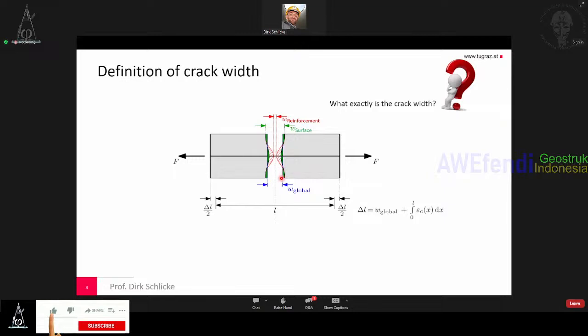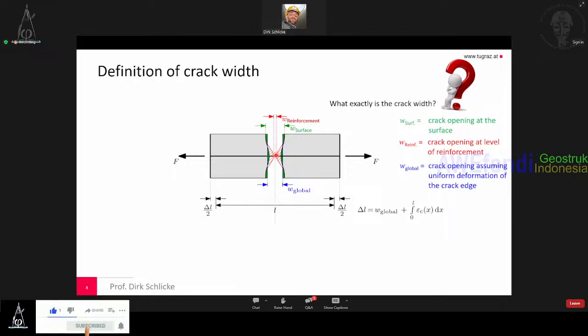marked in green. And overall, we can also say there is some sort of a global opening subject to compatibility of the member. So overall, the length change of the member, delta L, must be equal to the global crack width, so some uniform opening, plus what is happening in the concrete over the length. So there is a surface crack width, crack opening at the surface, a crack width at the reinforcement level, a very small one here near the reinforcement. But there's also a crack opening assuming uniform deformation of the crack edge.